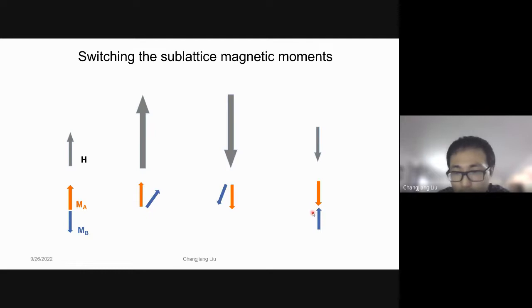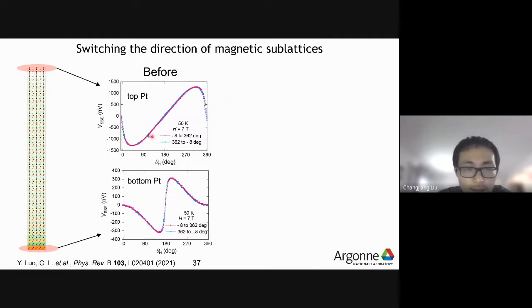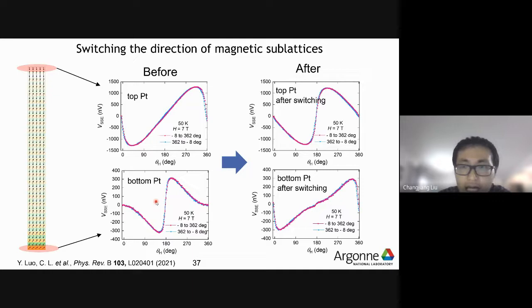By doing this manipulation, we can see how this polarity changes. This is before the manipulation. After the manipulation, we see that the polarity is switched simultaneously for both the top and the bottom surface. You see that. So this proves that this polarity difference is just due to the difference in the orientation of the sublattices.